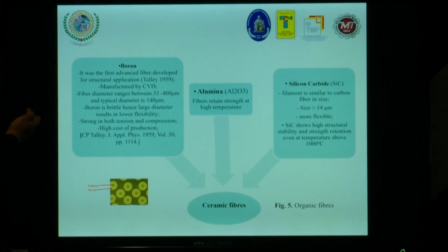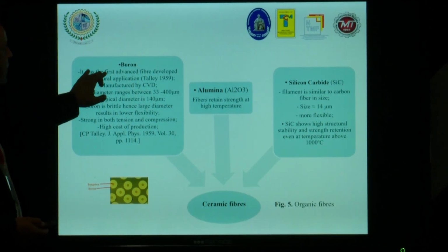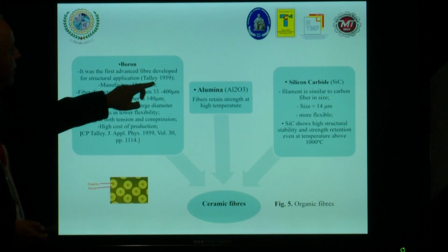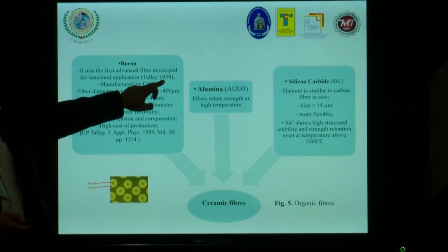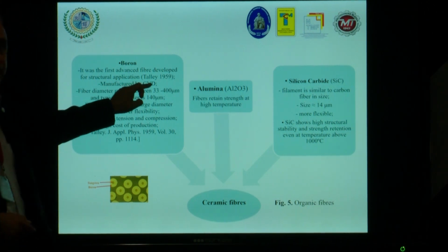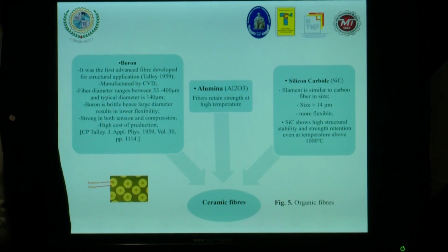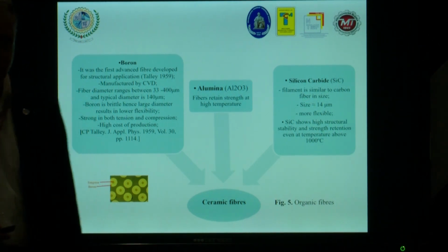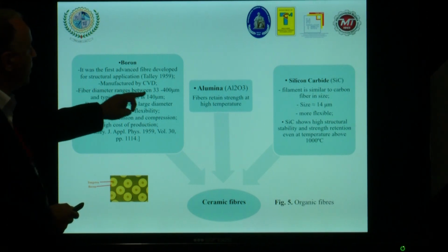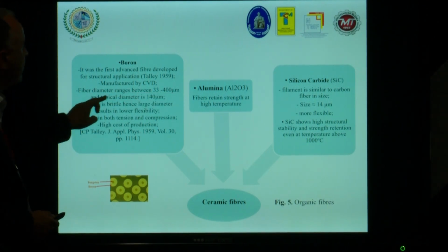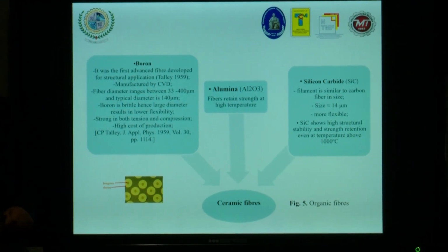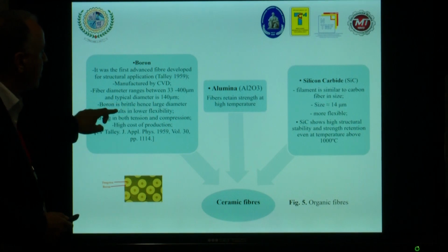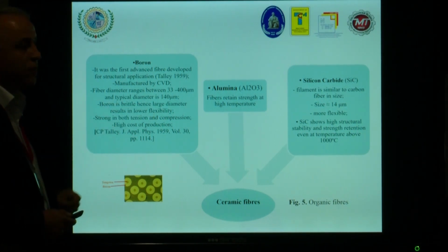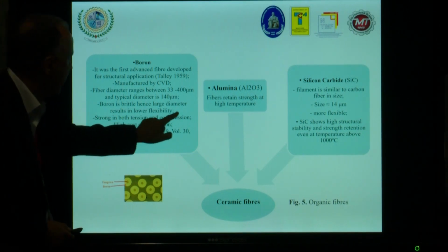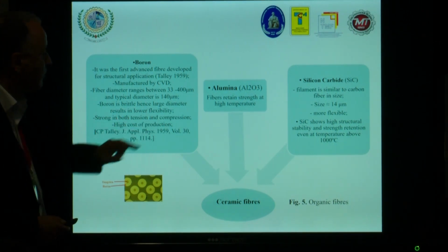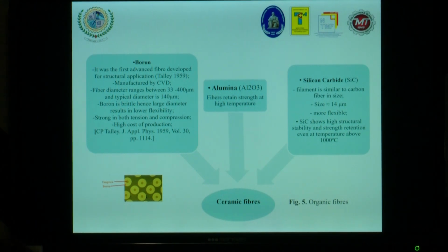Boron, ceramic fibers. You can see boron was the first advanced fiber developed for structural application. Look at the year, 1959. So many years ago. Manufactured by CVD, we already presented what the CVD process means, chemical vapor deposition. Fiber diameter ranges between 33 and 400 micrometers, and the typical diameter is around 140 micrometers. Boron is brittle, hence large diameter results in lower flexibility. Strong in both tension and compression, high cost of production in the case of boron fibers.